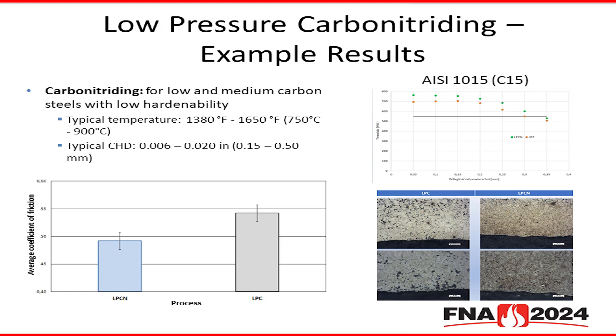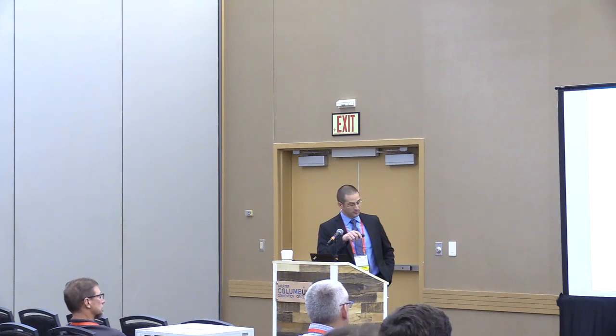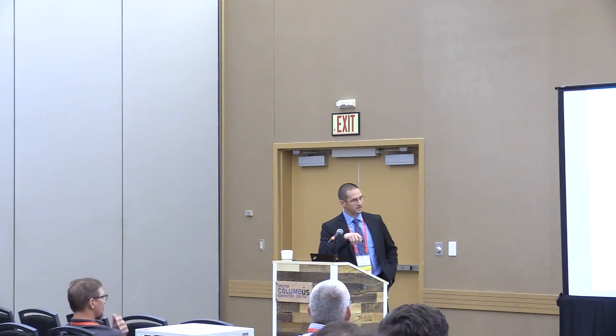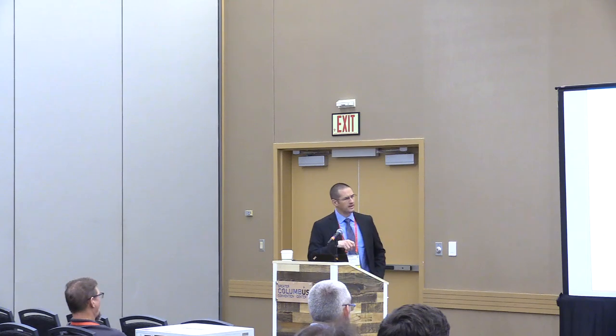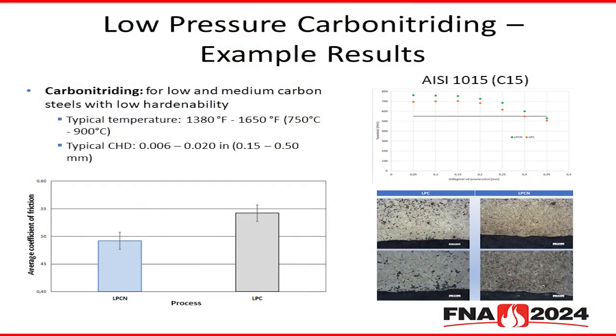we can note a few key differences. First, as was alluded to in the previous presentation, we can see a slight improvement of the average coefficient of friction. In a more practical sense, what does that mean? We have a more uniform and harder surface than a typical carburized surface. You'll note here that in this plot, the green dots indicate a hardness profile post LPCN, while the red dots indicate a hardness profile post LPC.